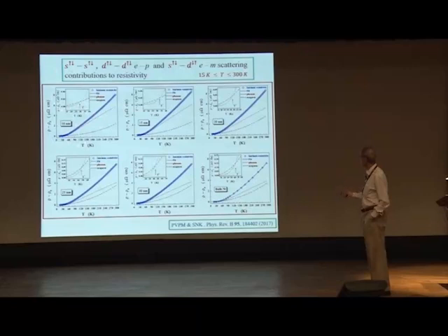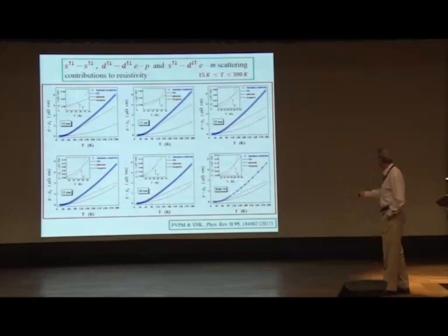Below that, the phonon term is much less important than the magnon term. But then there is a crossover, beyond which the phonon term picks up more than the magnon term. That crossover temperature shifts to higher temperatures as you increase the size.